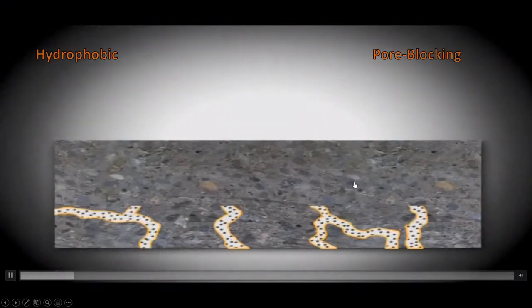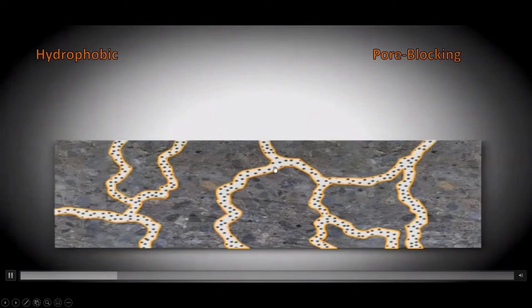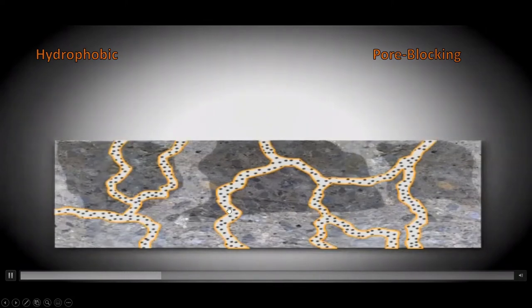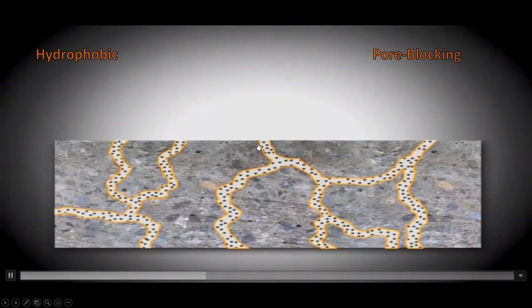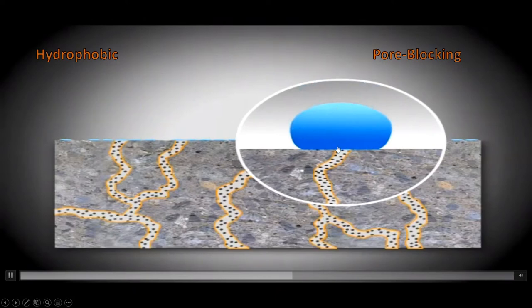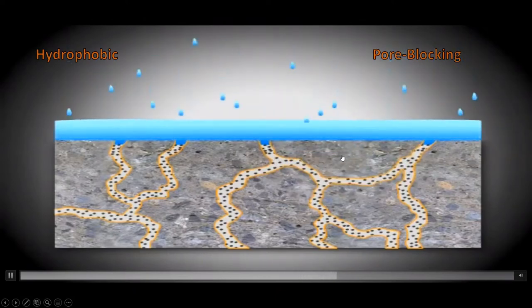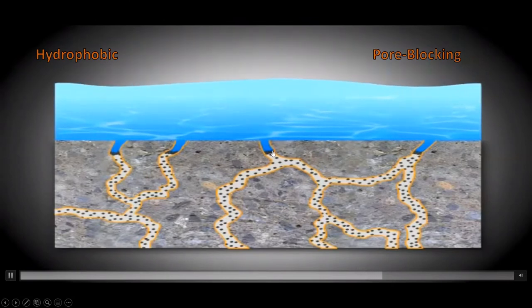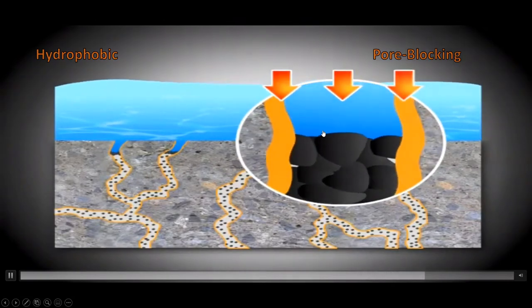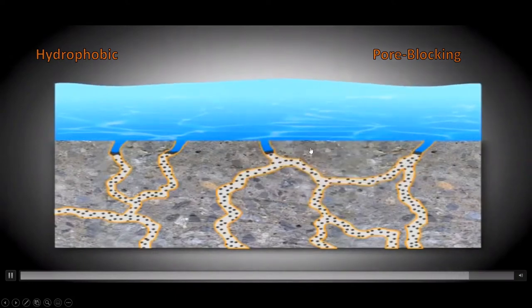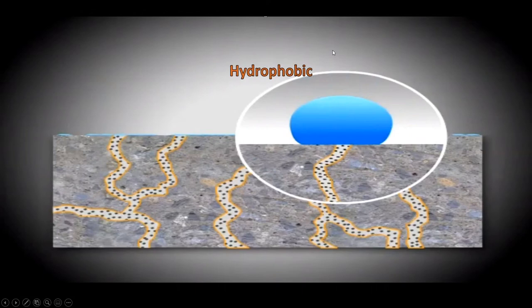Run this slide now. This is a brief explanation. So during the hydration phase, these are the capillaries that are being formed. The yellow lining here is the hydrophobic component, which reacts with calcium hydroxide and forms a nice water repellent coating. So when water lands on the concrete, it's literally repelled. If you subject that same concrete to a head of pressure, the secondary component, the pore blocker, is pushed ahead of the head of pressure until just a couple of millimetres below the surface, it will form the physical block and block the pores and the capillaries. Water won't go past the block because there is no suction.